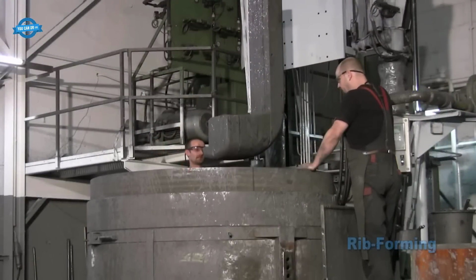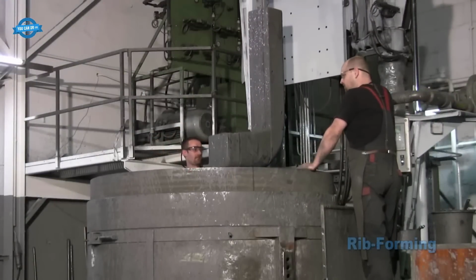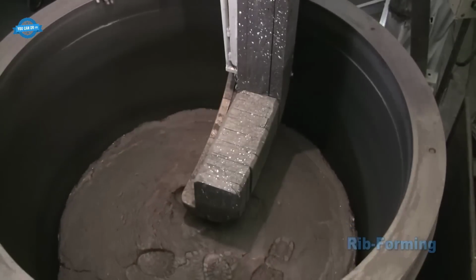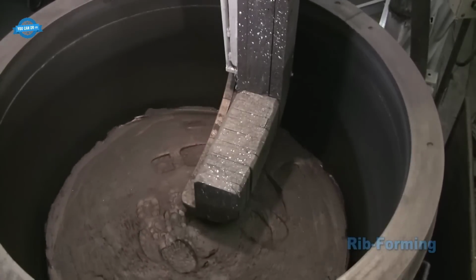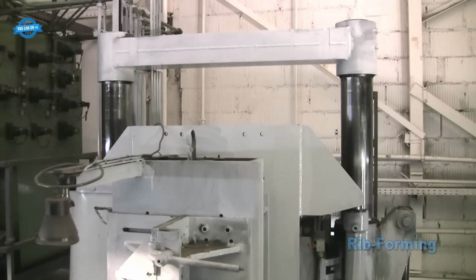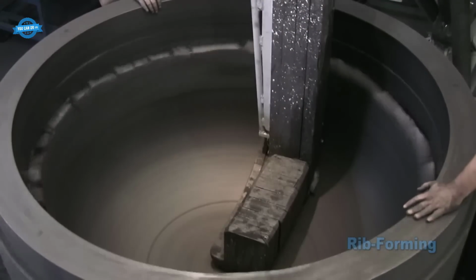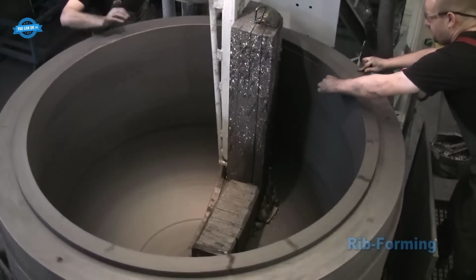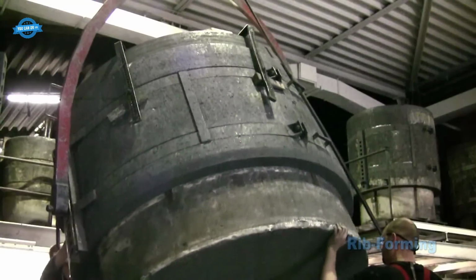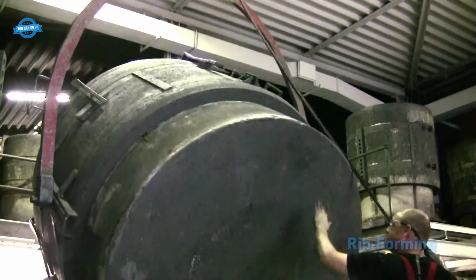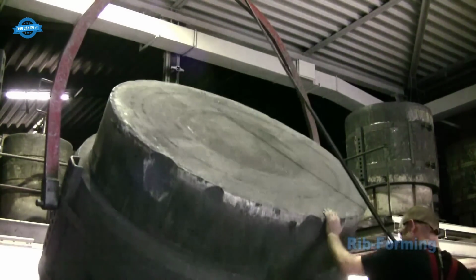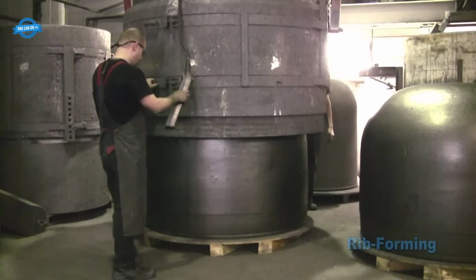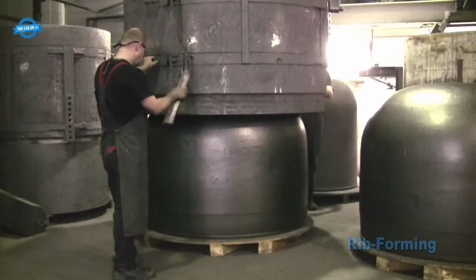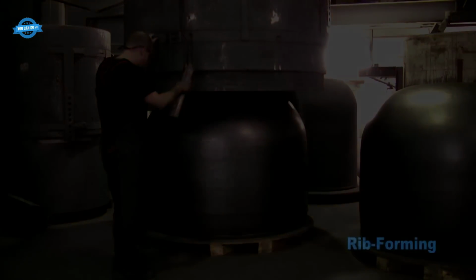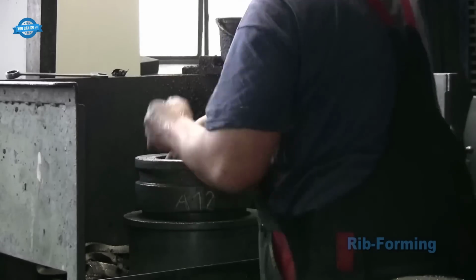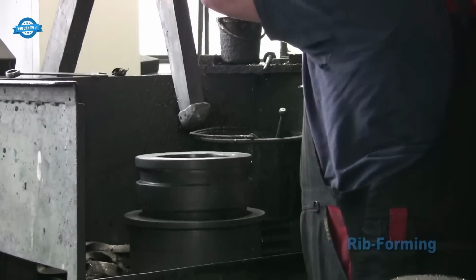The forming device, aptly named a rib, is lowered into the mold, which starts rotating as the process unfolds. A hydraulic ram presses the rib into the clay graphite material at the base of the mold. This exerts pressure of up to 5 metric tons, ensuring an even distribution of force. Rib forming results in crucibles marked by uniformity and precision, attributes that are challenging to attain through a completely manual process. The rotational movement enhances the distribution of material, and the automated approach streamlines the manufacturing process.